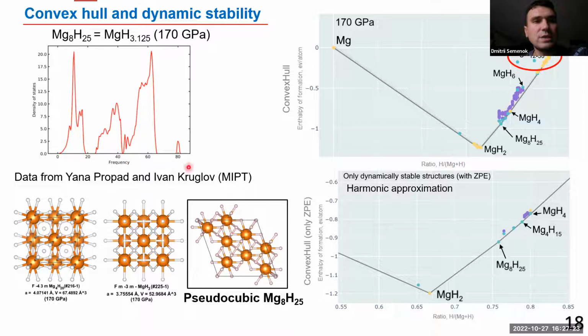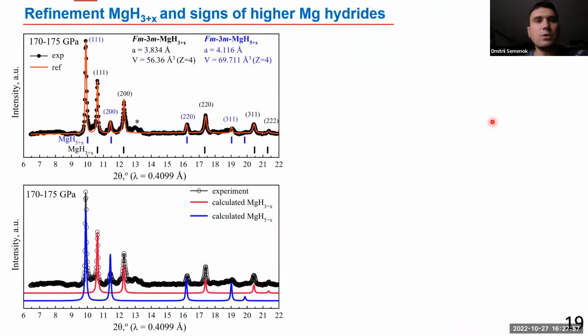This is a phonon density of states for this compound at 170 GPa. And the structure is different, but the X-ray diffraction pattern is the same. It's still a cubic diffraction pattern. Another thing I would like to point out here is the presence on the convex hull of a lot of magnesium phases with high hydrogen content. You can see it on the right part of my slide. It's the upper convex hull here. It's marked by a red ellipse here. It's important to note.